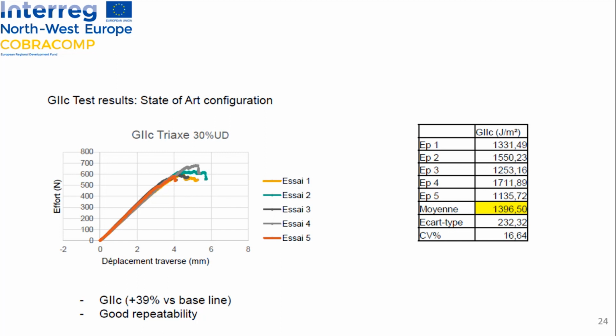So in conclusion, the axial fatigue test is lower on the braid structures, but with a new configuration where the two parameters involved in the decrease of performance, which are UD percentage and waviness of the yarns. The decrease of the waviness of the yarns, the result should be better with a new HQ braiding machine. For damage tolerance, G1C and G2C, the result is close to the baseline or better. It seems that the braid structure limits the crack propagation, and for G2C, the braid structure reaches the better result. So it's a good result for the project.